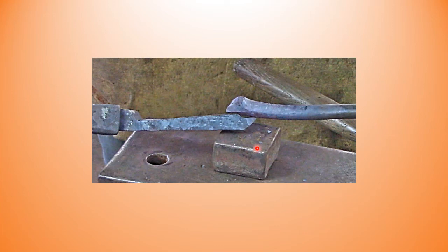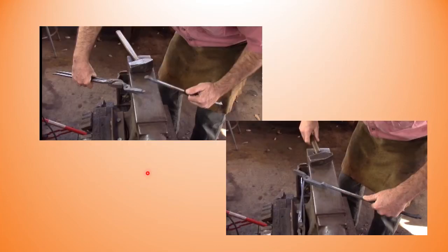So here are your two pieces scarfed and ready to be welded. Notice that the piece held by the tongs will start on the bottom and step up, and they will be held in place by the longer bar held in your non-hammer hand. The scarf should match up nicely or your first blow won't be welding, it'll be getting those to match up. If you start with a nice fit up at the beginning, your first blow will be a welding blow.